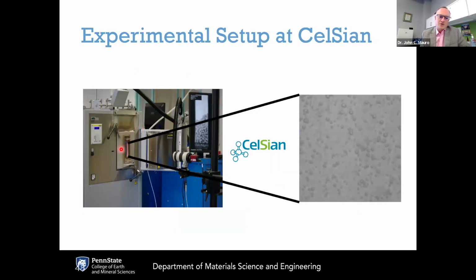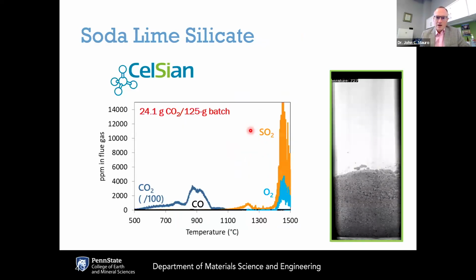This shows a picture of their setup with the furnace here, the window, the camera. And then this video shows the fining process of soda lime silicate. Fining is just the removal of bubbles as they rise up to the top. And then this video on the right, this shows the batch to melt conversion process for a standard soda lime silicate. The temperature in the upper left is the current temperature in degrees Celsius.